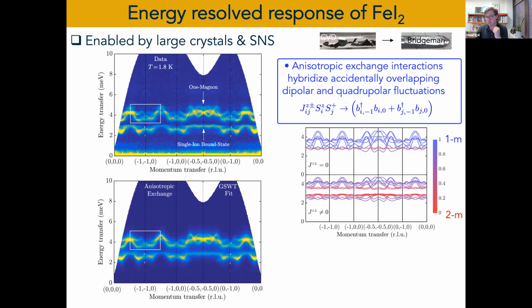In this system, we have two types of single particle excitation, one magnon and two magnon bound states, or single ion bound states. These are in principle two different sectors, but now because of anisotropic exchange interactions, these two sectors are coupled, and this J_z± interaction maps in Schwinger bosons into b_{i,−1}† b_{i,0}. So it's essentially creating a quadrupolar fluctuation from a one magnon state.